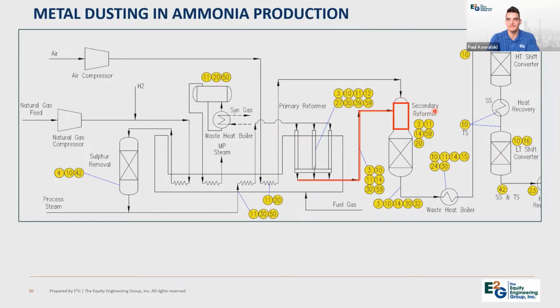And based on experience, it appears that combustion, or a combustion environment, leads to a more severe metal dusting environment as opposed to, say, in the transfer line where combustion isn't occurring. So this is a very severe spot in the secondary reformer for metal dusting to occur. And typically this would be a 2 1/4 chrome base material.